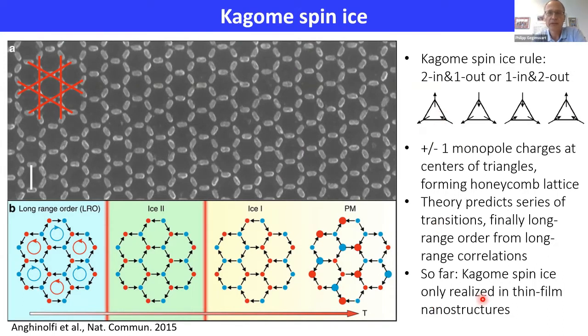triangular unit. Now the theory predicts a series of transitions as we cool down such a Kagome spin ice. So once we fulfill the ice rule, this separates the ordinary paramagnetic state from the first Kagome spin ice state. But then there is a long range order of the magnetic monopoles in 2 steps before we reach this state here, where by the blue and red dots, we indicate the charge of the monopole at each center of the triangular unit. If you connect the centers of the triangular units of the Kagome lattice, this gives rise to a honeycomb lattice. And this is here the full order of the magnetic charges in this honeycomb lattice of the monopoles that we have in the Kagome spin ice.